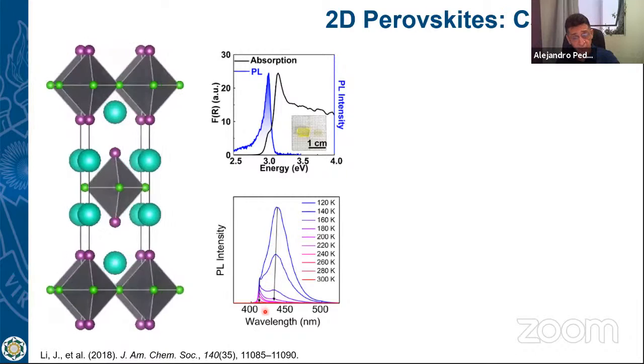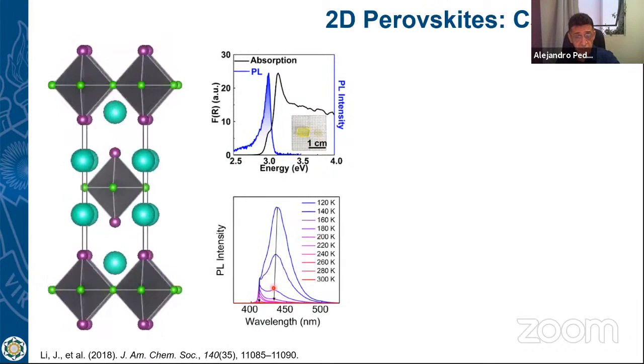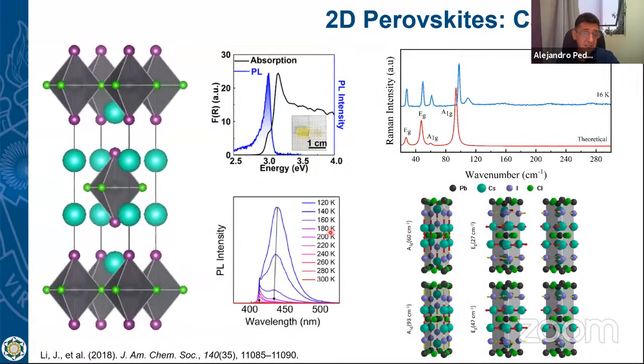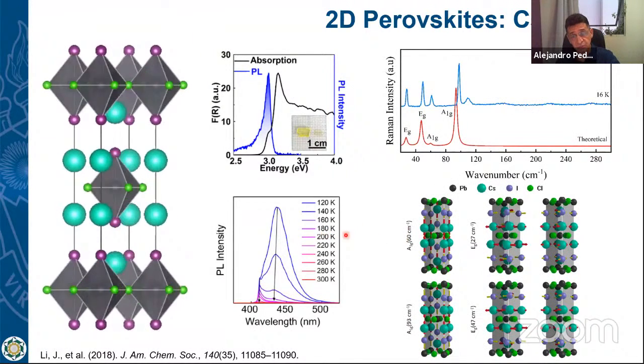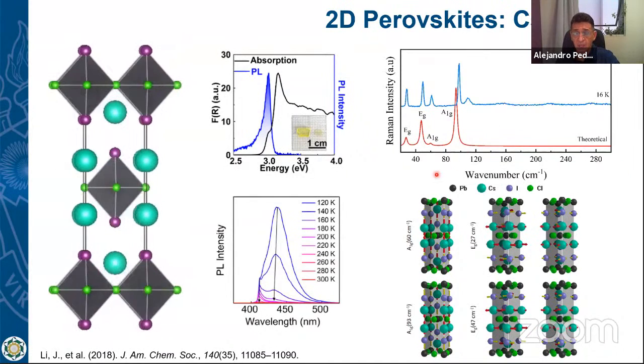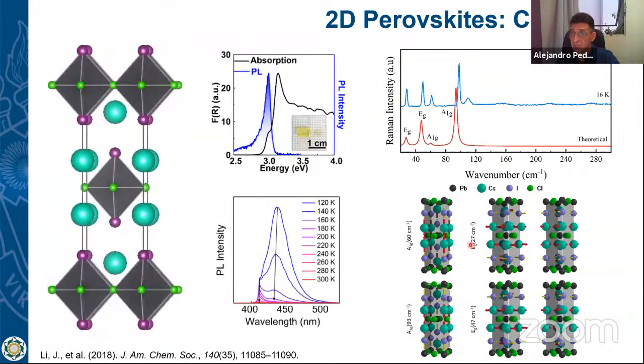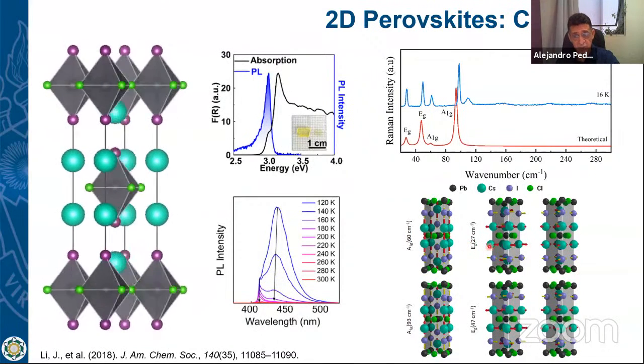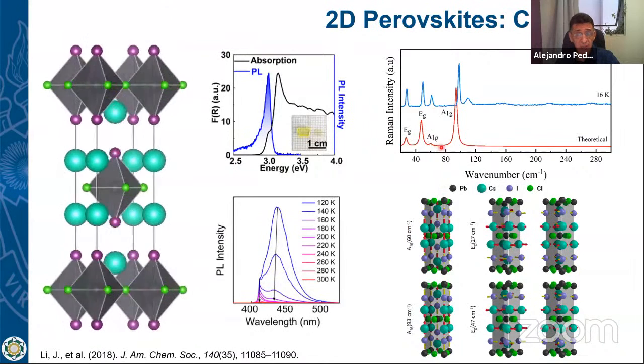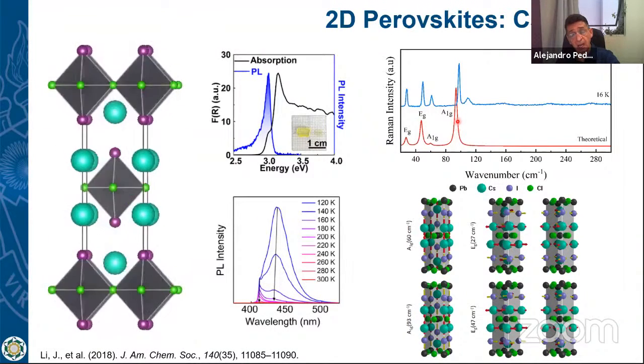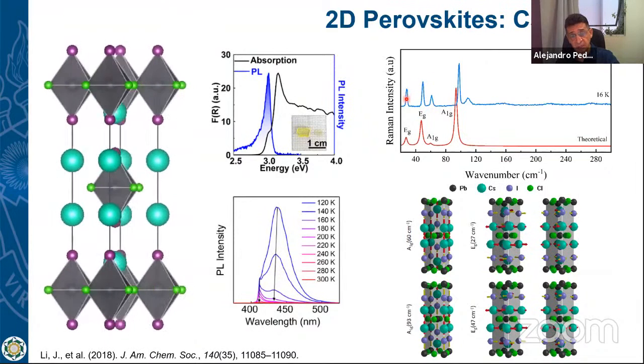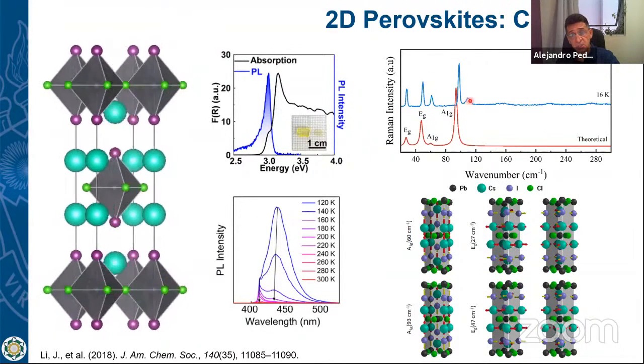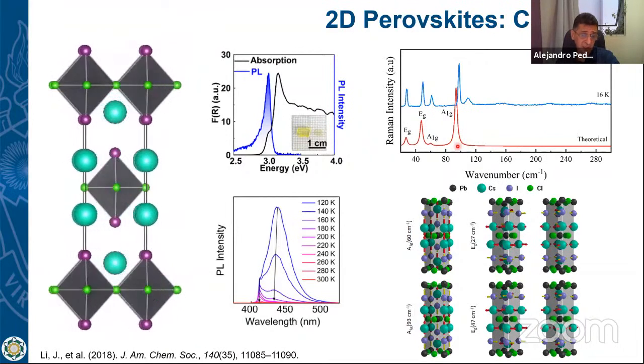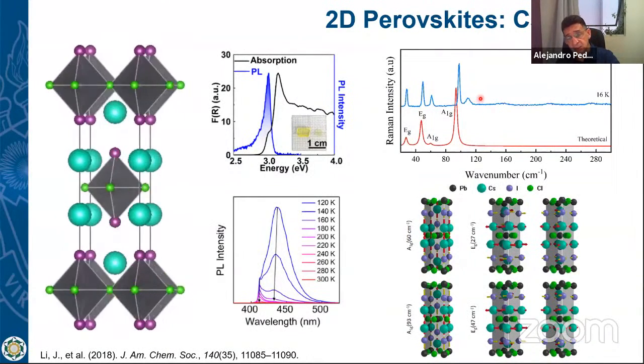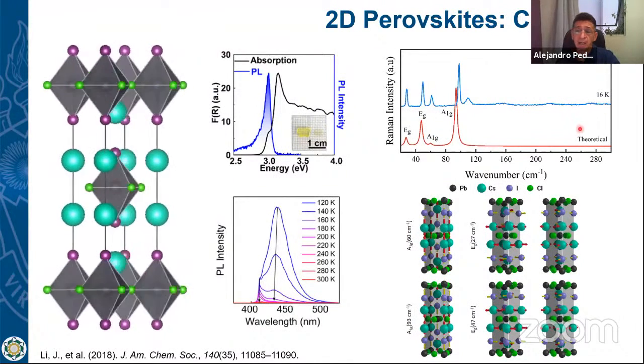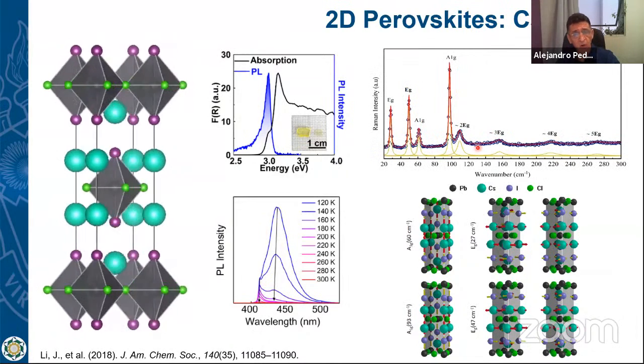And you can see that the photoluminescence is changing as a function of the temperature. But in principle, no phase transition can be observed in this material. With this theoretical calculation, again, you can see the vibrations of the material, and those reproduce quite well those observed experimentally. But there is one here which is not predicted in the calculation, and this very weak band can be associated to something called overtones.